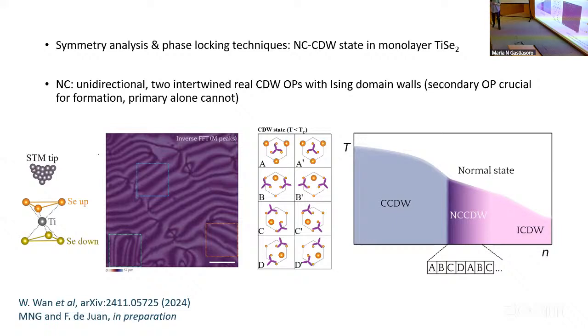There is something very cute that happens when there is an incommensurate charge instability nearby. This charge modulation is typically a multiple of the lattice spacing, but sometimes the system prefers to do it with any rational number. So it's not every 2 or every 3, it's every 2.2, for example. And the cool thing is that going from a natural number to this other possibility has to go through what's called a nearly commensurate state. In such a state, the system basically flows through different ground states. So what you're looking at here is basically domains of the system going through the different ground states. It's like A, B, C, D, A, B, C, D.